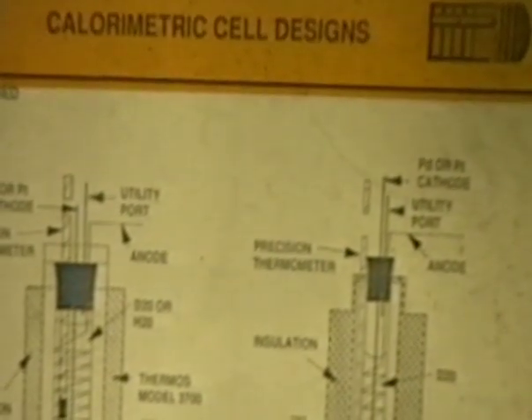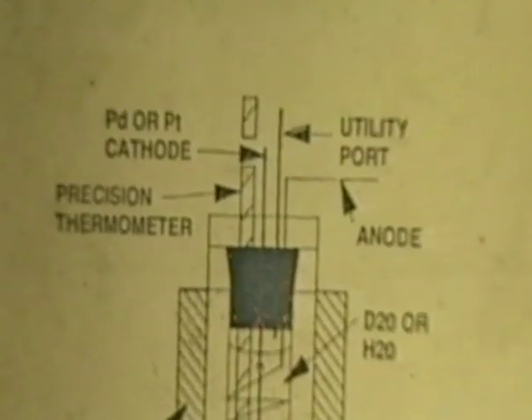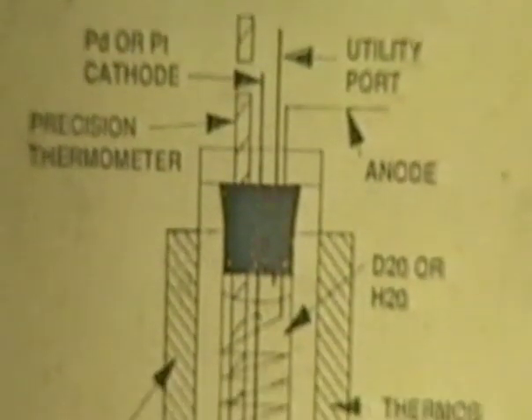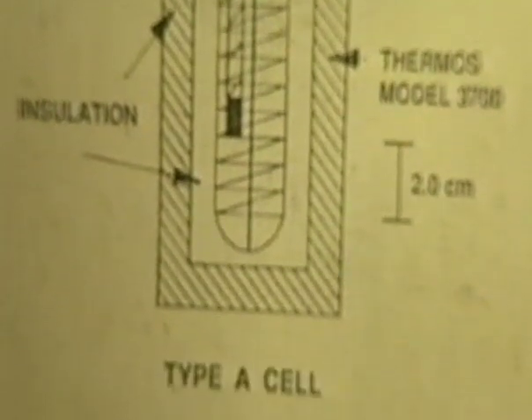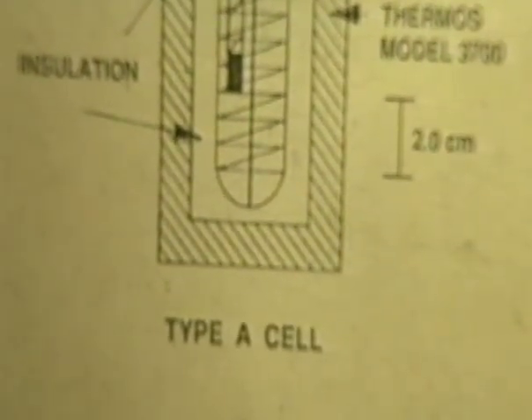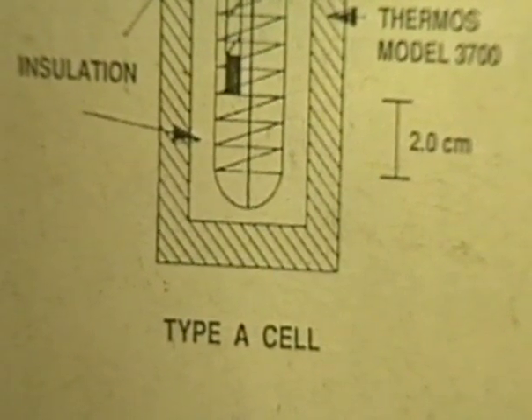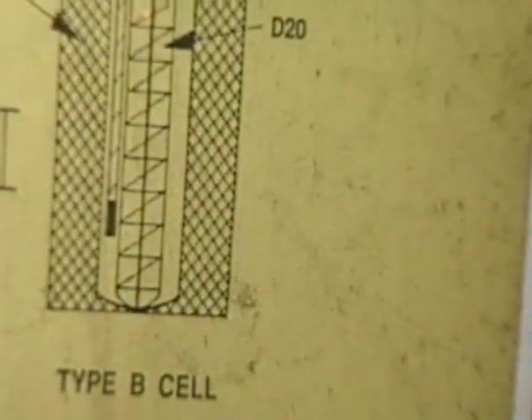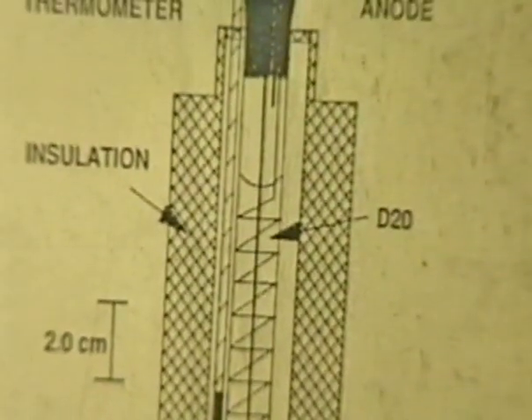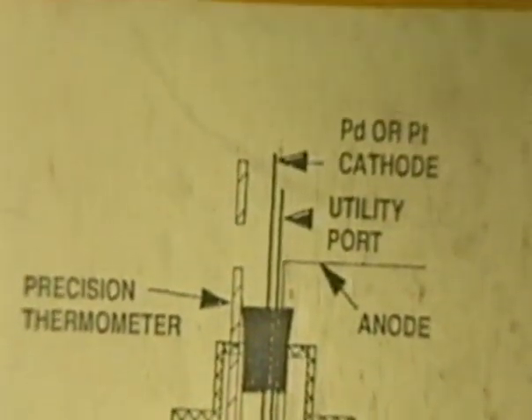And we started off using various calorimetric designs, but basically, we had one type where the thermometer was inside the cell, and the second type where it is outside the cell. So in this case, it's an integrating calorimeter. The volume of liquid, if we used regular water out here, was about 60 cc's, where we had about 18 cc's inside. So it was not very sensitive to the liquid level. Where this is very sensitive to the liquid level and created a big problem for us.